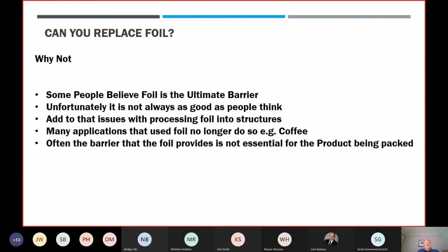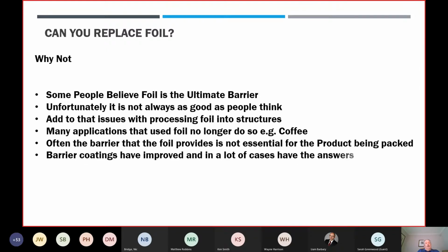Often foil is in the structure because that was what was around at the time. And people don't really question, do I need that absolute barrier that a nice thick layer of foil would provide? And the answer is, in a lot of cases, no, you don't need that. But you have to have a will and a commitment to push the barriers to see if you can replace the foil and if that gives you enough barrier for the product being packed. And barrier coatings have improved, and in a lot of cases have the answers.